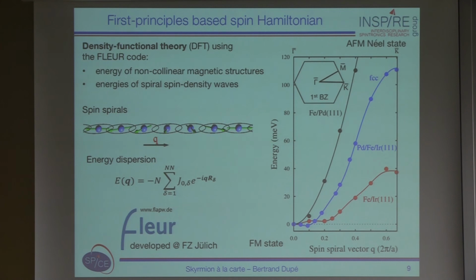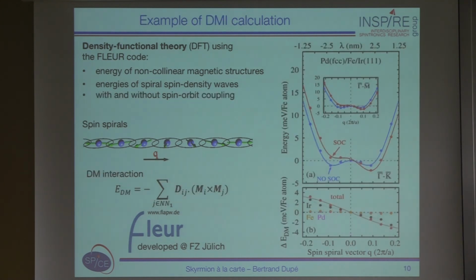So what you can do after you have this dispersion curve is apply spin-orbit coupling. I show you here a reminder of this energy as a function of Q, but this time we don't go to one edge of the boundary of the Brillouin zone. We rather go to a left-rotating or a right-rotating spin spiral. The left-rotating spin spiral is shown on the left here with a minus periodicity, and the right-rotating spin spiral is shown on the right with a plus periodicity.